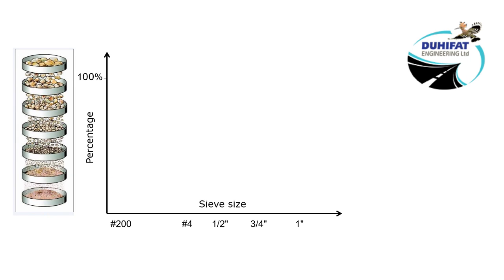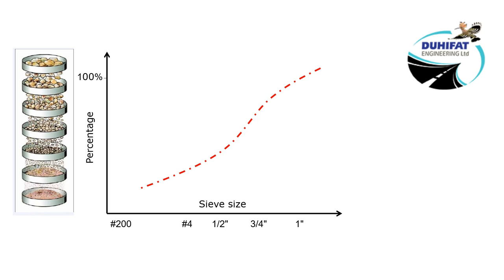We can saw out a piece of the asphalt on site, and after extracting the bitumen, we can trace the aggregates gradation line. By comparing it to the factory original line limits, we can see and calculate the differences in every sieve and determine the exact amount of segregation.